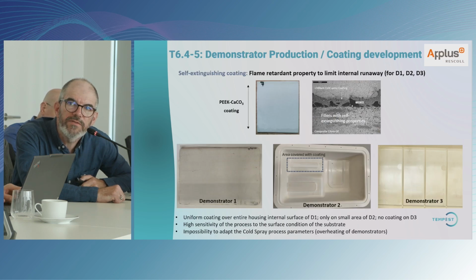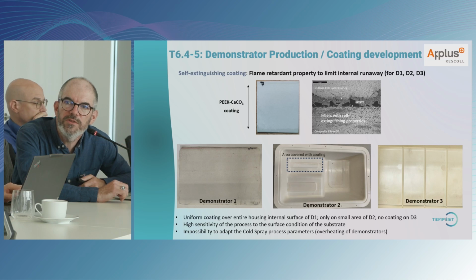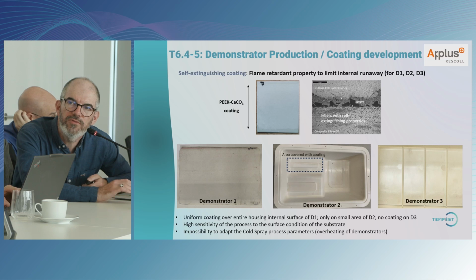Third one was the self-extinguishing coating with flame retardant properties, so a mix between PEEK and calcium carbonate. On D1, it was possible to get a nice coating, but on D2 and D3, it was harder. And it's mainly due to the fact that we observed overheating of the demonstrators, mainly due to the mix used for the coating. So for this, it was pretty much more challenging compared to the two other coatings.